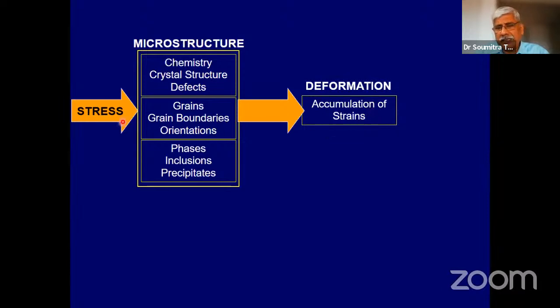What happens is when there is a sustained application of stress, maybe cyclic in nature, monotonic in nature, the environment, other materials that are there in the neighborhood, etc. This initiation of damage further interacts with the microstructure. The strain interacts with the grains, the grain boundaries, with the inclusions, with the precipitates, and this, in a sustained and cyclic manner, increases the damage. So as the external stimulus is sustained, this will further interact and cyclically be processed within the microstructure and cause damage.